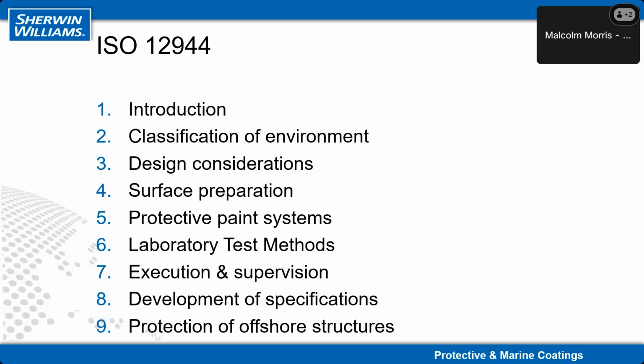And the key ones there are part 2, classification of the environment, design considerations we mentioned. It suggests best practices to avoid corrosion traps. Then surface preparation, because that's a key point to having a successful coating system. Protective paint systems are suggested for different environments and durabilities. And then all sorts of ancillary sections about proving test methods, execution, and specifications. Part 9 was added on. That used to be a separate standard. That's specifically for offshore structures, which are obviously very corrosive environment.